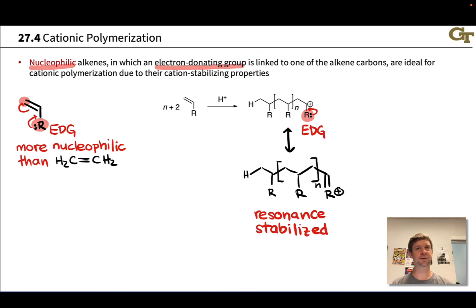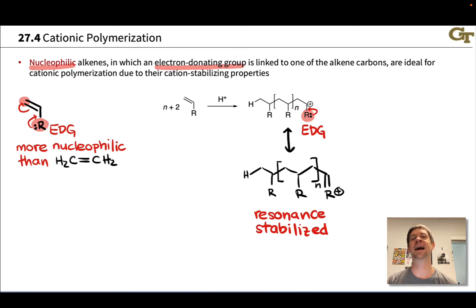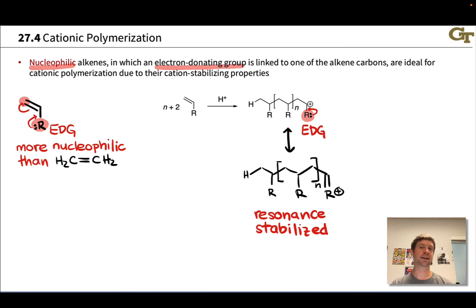If that cation is highly reactive, it could add solvent or do some other reaction that terminates chain growth, leading to an oligomer rather than a long polymer — or, if we want a living polymerization, the cation keeps getting used up, which is undesirable. Stabilizing the cation with an electron-donating group is therefore advantageous. Nucleophilic alkenes are better for cationic polymerization, while electrophilic alkenes are best for anionic polymerization because of their anion-stabilizing properties and relatively high electrophilicity as neutral monomers.